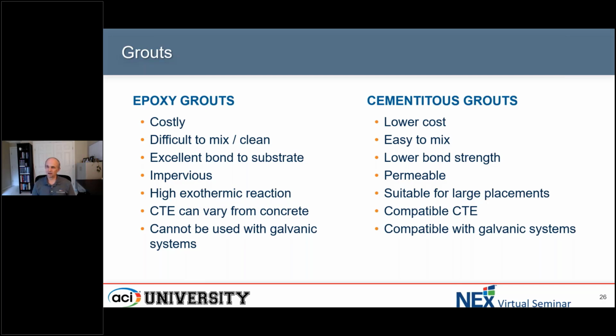On the other end, cementitious grouts are generally lower cost materials, a lot easier to mix using just conventional mixing equipment, and a lot easier to apply. But again, they're lower in terms of bond strength, so there can be some durability issues. They may not have quite the life that an epoxy grout might, but if done properly, they can still result in a pretty quality concrete repair.